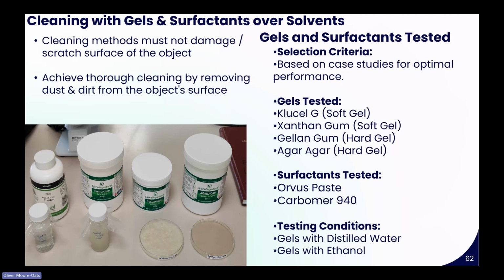Another cleaning method that we use, and I'm going really quick about it because I don't have much time, is gels and surfactants, because we also want to promote some green chemistry. Based on the knowledge that we have, we use conservation grade surfactants and gels. We can see the list before. What's important is that we can use soft gels and hard gels, where you can take a piece and use it with abrasion techniques. We test with two parameters: we create gels in distilled water as the standard, and then we use ethanol as an additional test to evaluate effects on performance as well.